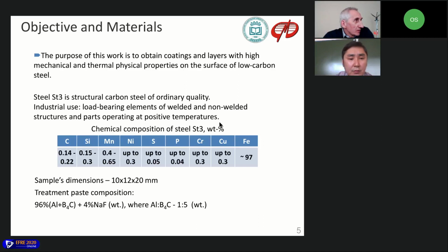Steel ST3 was used as a tested material. It is used for load-bearing elements of structures and parts operating in positive temperatures. So before experiments, samples were cut into rectangular pieces, and for treatment paste we used powders of aluminium and boron carbide. In addition, sodium fluoride as an activator, where aluminium and boron carbide ratio was taken as 1/5.